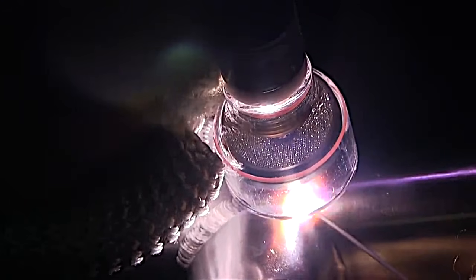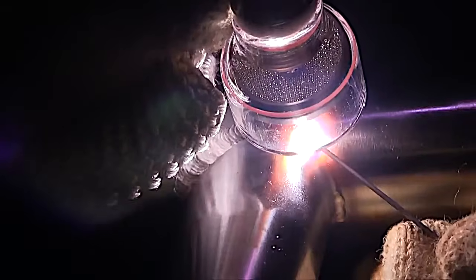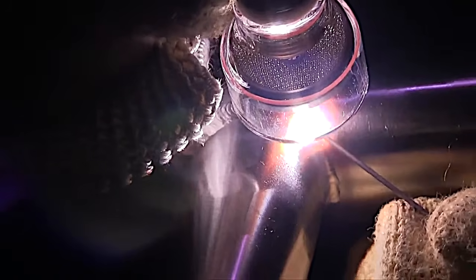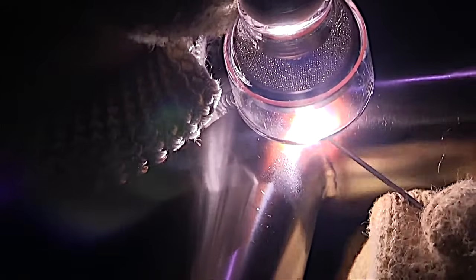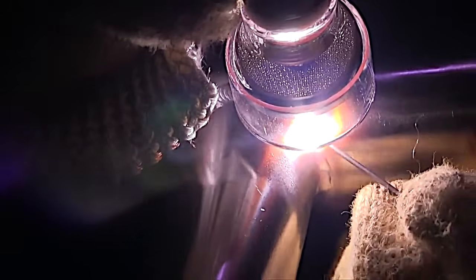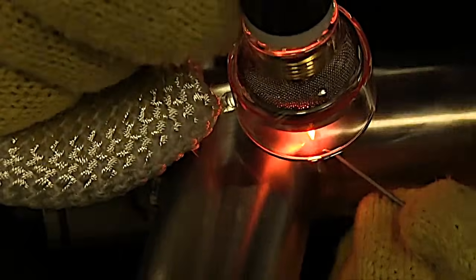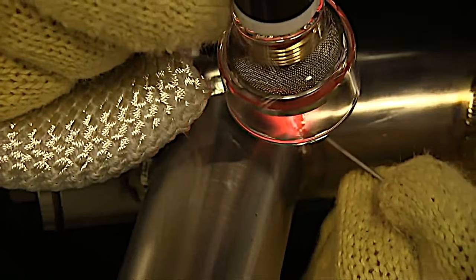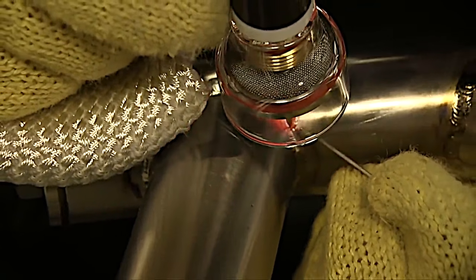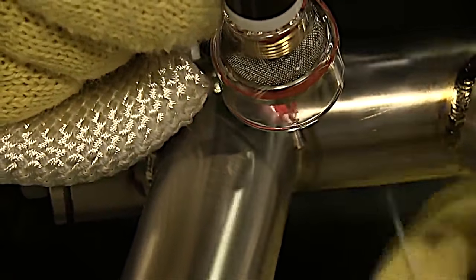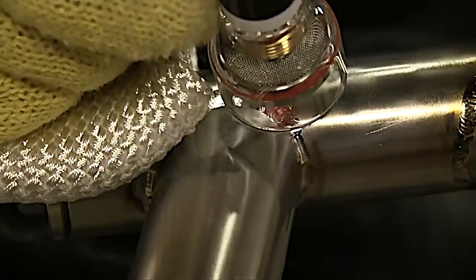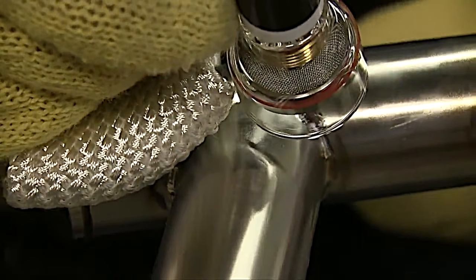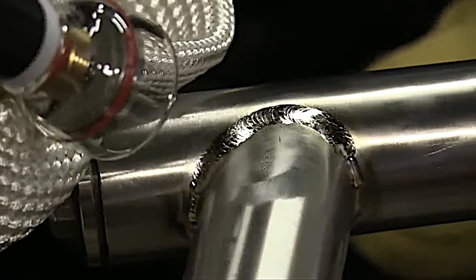This is my friend Mike Zancanato welding on a titanium bike frame, taking his time. The main thing here he's shooting for is a silver discoloration-free weld. And that means holding the torch still with a really long post flow. You got to be patient with titanium. If you pull your torch away, you'll discolor that weld. You want about 30 seconds of post flow there.